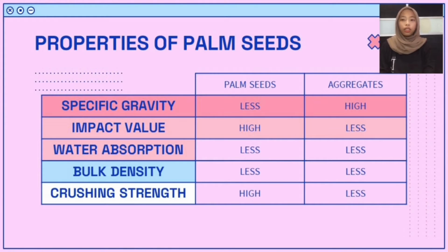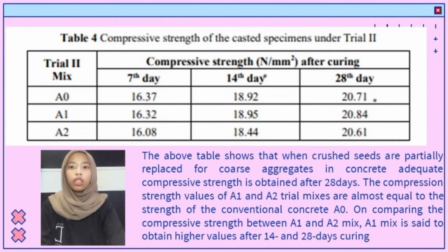The observations from the methodology conducted helped to analyze the properties of the palm seed. The specific gravity, water absorption, and bulk density values were found to be lesser for palm seeds when compared to coarse aggregates. The impact and crushing strength were found to be higher for the seeds. It is important to know the strength properties of the casted specimen to know the possibility of using palm seeds in concrete as an alternative for coarse aggregates. So, from the trial 1 specimen, it can be concluded that the palm seeds cannot be used without crushing.